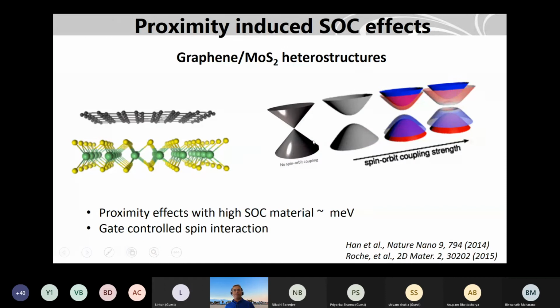So how to induce spin orbit coupling in graphene? Lots of experiments have been done to put metals like platinum or heavy metals on graphene to induce spin orbit coupling. But that didn't really come out well because it also degrades graphene properties. So what is a good idea, developed in many theory papers first, is that when you put graphene with a 2D material like MoS2 here, it's a van der Waals force, so you are not affecting much the graphene electron mobility, but what you can do is that due to proximity, you can open a gap. And if you increase the spin orbit coupling in these systems, what can happen theoretically is that you can create the spin splitting of the bands. And if you increase further, the band should invert and it should be a topological insulator.